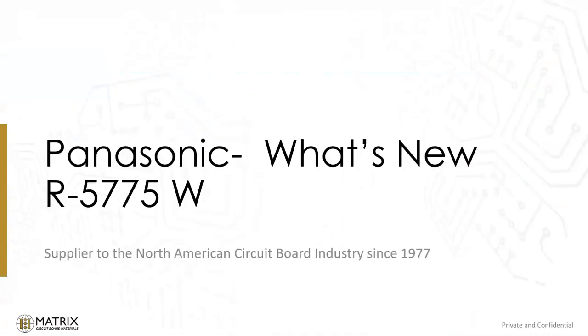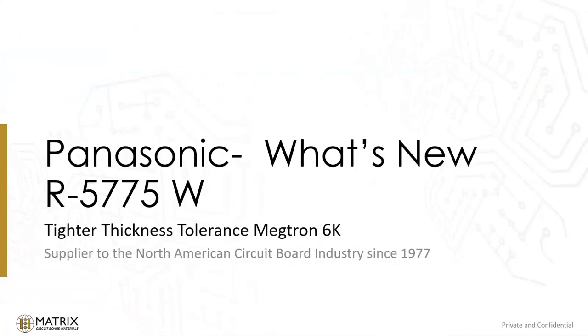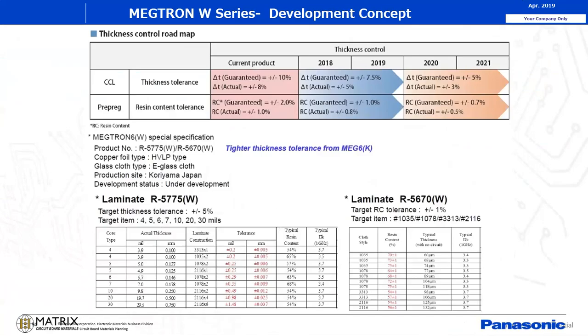This was one that was on Bob's list of topics that we happen to have, and we can introduce that. The R5775W, which is a tighter thickness tolerance Megtron 6K. As impedance requirements are getting tighter and tighter, one way to address that is to tighten up some of the tolerance. The IPC spec, of course, doesn't go through the tighter tolerances, but here we're looking at a subset of the laminates that are identified as something we can offer as tightened up. So the thickness tolerance is plus or minus 5%, and also with the prepregs as well, so a tighter tolerance on that resin content. Panasonic does a real good job with controlling both the thickness tolerance for laminate and also the resin contents on prepregs. But here is a controlled, identified way that they've come up with to help get to those tighter impedance projects.